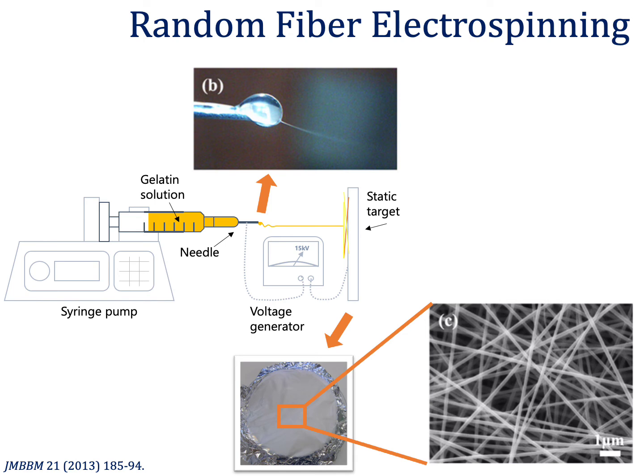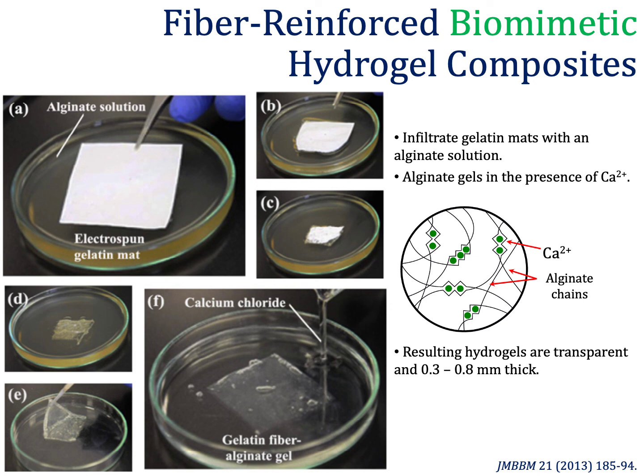So we use gelatin in an acetic acid solution, so something that's not terribly toxic and not a horrible solvent. We use a 15 kilovolt voltage generator and a static target to make randomly oriented gelatin fibers, which are quite comparable to the collagen fibrils. And then we infiltrate these fiber mats with a hydrogel. In this particular case, we're using alginate, which is a seaweed-derived sugar, and it's physically cross-linked with calcium. We've also played with chemically cross-linking the gelatin itself, but I won't have time to go into those results today.